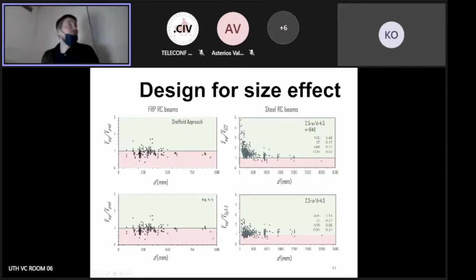Now you might say that, okay, all this work for only shifting a few data points up. Yeah, that's maybe true, but we don't really have that much data. It's not easy to go to the lab and test a beam which has 800 millimeter size. It's kind of a lot of work. But the most interesting thing that I found in my research really is that I used the same equation for the steel reinforced database. And what I observed for some reason is that it can be directly applied to these steel reinforced concrete structures, and as you see, can reduce the coefficient of variance by as much as 25% actually.